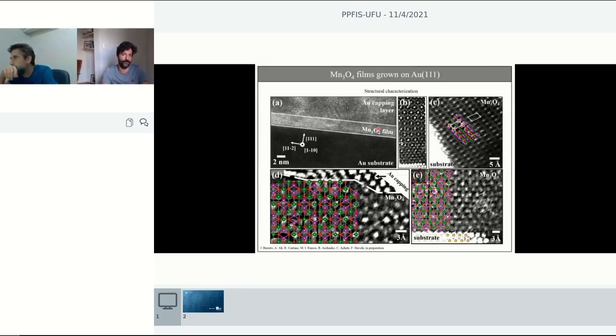For those of you that are not familiar with transmission electron microscopy, what we're doing here, we prepare a film, we cut this with a focused ion beam microscope. Actually, Brown and his group do that there in metal. And then you can cut this film and look at the side of the film. So then we have both pieces of information. We have the top surface information with our microscope combined with this cross section that add up to find the structural termination of this film in both ends, on the surface end and also at the interface end with the substrate.